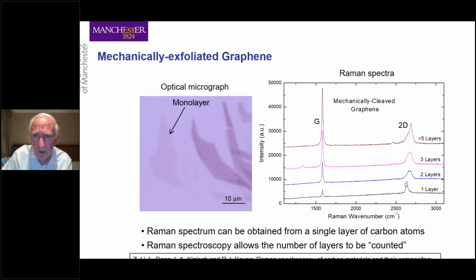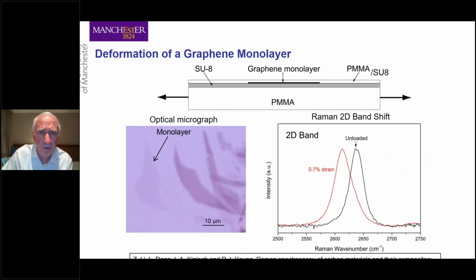Monolayer, you get this 2D peak is very strong, the G peak is weak. Bilayer, it's the other way around. The G peak is strong and the 2D peak is weak and also shifted slightly. So you can use it for counting the number of layers. And of course, that's not really anything to do with strain sensing, but it just shows how you can use the technique. Let's look at strain sensing.